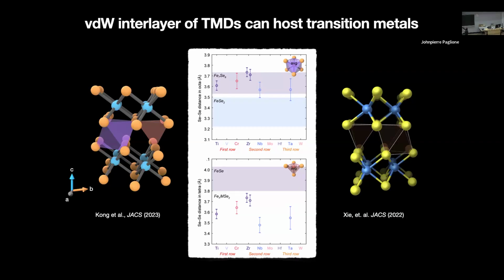Not so for the tetrahedral sites, which are generally much smaller than what you find in, say, iron selenide. But in the zirconium case, you have the largest tetrahedral site. And so it turns out that iron-intercalated zirconium selenide does give you about 20 or 30% occupancy of the tetrahedral site. But by and large, the intercalation goes into the octahedral site. That's the main point, with the exception of a few others.